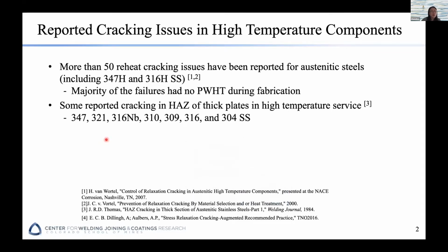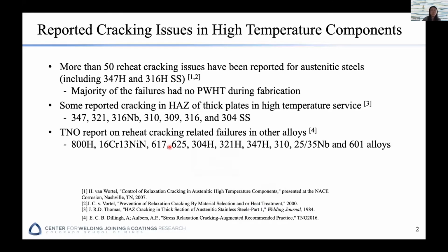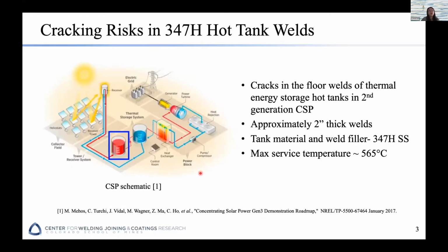Okay, so let me enable my laser pointer. All right, and we also noticed that the TNO reported reheat cracking failures in other alloys like nickel-based superalloys. A lot of them are listed in here. And the majority of those materials that have reported issues are precipitation strengthened, meaning they have certain precipitates distributed in the microstructure to make the material stronger. And the particular material that we are working on is the 347H stainless steel.